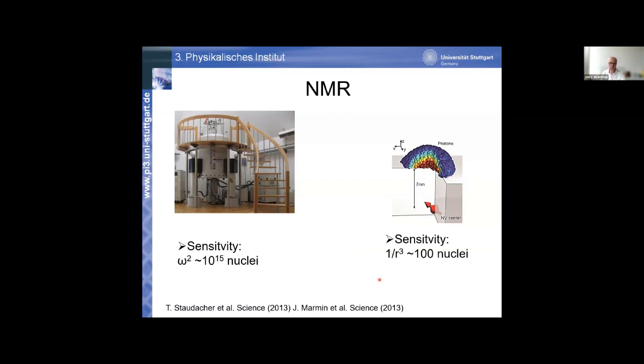All right. So actually the machines we are competing with are standard machines measuring nuclear magnetism. These are the nuclear magnetic resonance machines you see here. These machines are going to ever larger magnetic fields for two reasons. One is sensitivity, because the sensitivity scales with the Larmor precession of the nuclear spin squared. And in these big machines here, which almost go to 20 Tesla of an external magnetic field, 800 megahertz to be specific, you have a sensitivity of 10 to the 13 to 10 to the 15 nuclear spins. Our system is way easier, so it's way more compact. It's actually a very simple setup. The sensitivity we get is easily 13 orders of magnitude better, right? There is no comparison in terms of sensitivity.